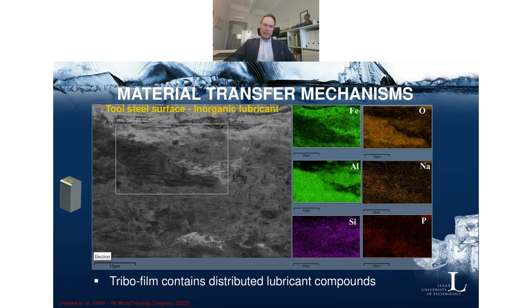And when comparing the appearance of this tribofilm, it looks quite different compared to the dry test. So this is more granular, it's not as strongly adhered to the surface. So there is an added value in terms of the ease of removing the transfer material later on by utilizing a lubricant. So it has to be looked upon from different angles if you are trying to decide whether or not to go for a lubrication strategy in this hot forming process.